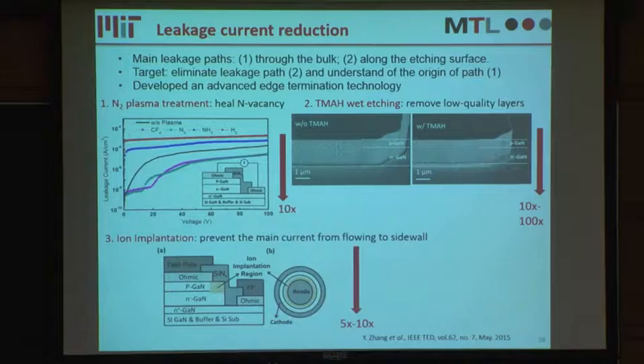The third process we use is ion implantation. We make some ion implantation rings at the edge of this ohmic contact that penetrate into the PN junction. Because these implanted regions are quite insulating, this can prevent the main current from flowing to the sidewall.